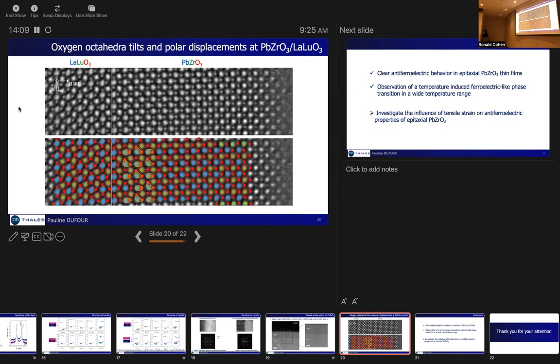In the first unit cell, this oxygen octahedral tilt in lead zirconate gives rise to a polar displacement, which is highlighted here by the yellow ellipses. Maybe it's even clearer on the raw data here. So it seems that in the first unit cell, we have a polar displacement of the lead ions. However, for the rest of the unit cells, it was difficult to probe the antiferroelectric state of lead zirconate. So these bilayers are promising for the study of the emergence maybe of some antiferroelectric state, but it requires further investigations.